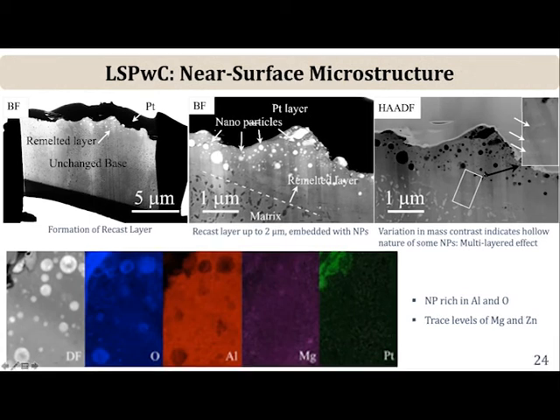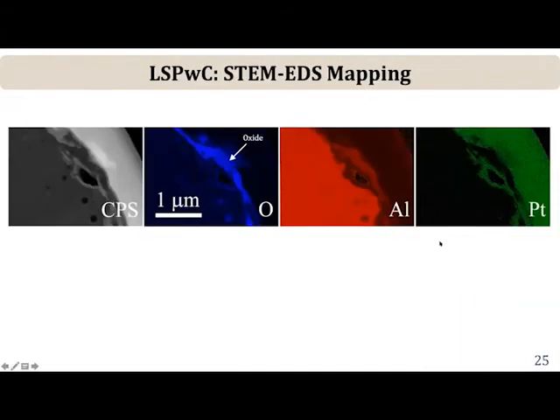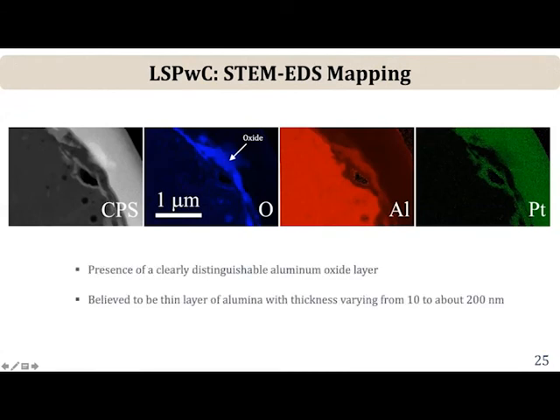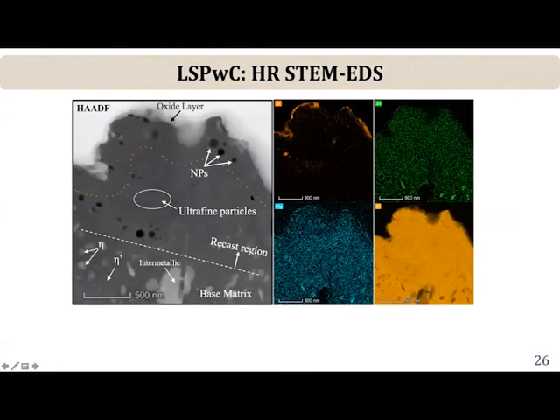So you have a remelted region from the repeated peening. Now, the other important feature that one sees, apart from this recast layer, which is now free of these big precipitates, is a very thin layer of aluminum oxide on the surface. So two important things: a clearly distinguishable aluminum oxide layer, which varies in thickness, and these aluminum nanoparticles. The previous set of images were done in a scanning electron microscope. These images here are from a scanning transmission electron microscope at 200,000 volts, much higher resolution. So you notice features that are very similar, except in much more detail.